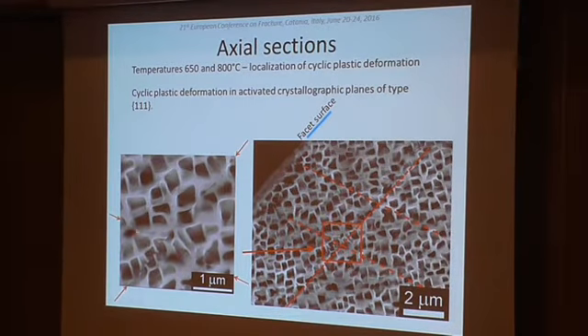So here are some examples of fine observation of this axial section, where we were able to find evidence of localization of cyclic plastic deformation along the slip planes of type 111, which are visible here in this detail from this area. And you can see activated slip planes with nice shearing of precipitates.